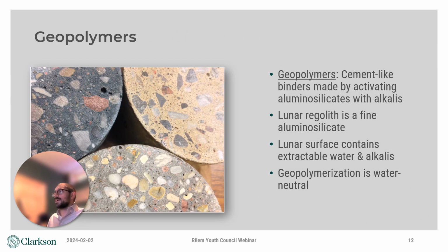Fortunately, over the last several hundred years, concrete researchers have developed a pretty robust toolbox of technologies that can be used to make concrete. One of those technologies is geopolymers, or alkali activated concrete. Geopolymers are cement-like binders that are made by combining an aluminosilicate material with an alkaline activator. On Earth, we make geopolymers with fly ash or slag cement, but this technology works with just about any aluminosilicate material, of which the lunar regolith happens to be one.